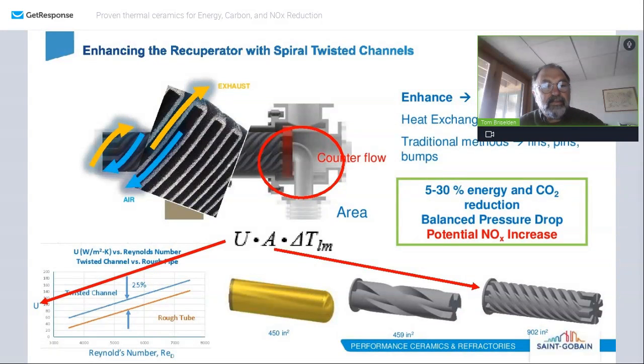Extending the concept of the twisted tape to that of a heat exchanger, a twisted channel is shown to be an effective means of increasing both surface area and overall heat transfer coefficient simultaneously. The twisted channel imparts a velocity vector perpendicular to the heat transfer surface area that almost acts like a jet. This increases the Nusselt number and the overall heat transfer coefficient by about 25%, as shown in this diagram on the left. Increasing the surface area with the assistance of additive manufacturing allows for a significant change in surface area as compared to fins and bumps.